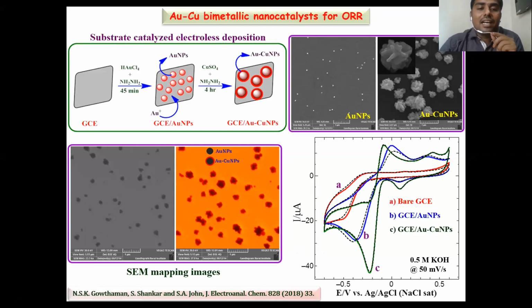So we utilize the fabricated electrode for the O2 reduction reaction in the KOH medium. In the previous case, we used the sulfuric acid medium. In this case, we used the alkaline medium. So here, the gold copper bimetallic nanoparticles fabricated electrode exhibited higher catalytic activity towards the O2 reduction reaction when compared to the bare GCE and only gold nanoparticles.